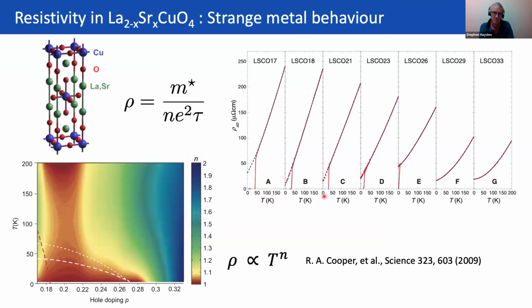So here's some paper from Nigel Hussey, who's going to be talking tomorrow. This is an old paper in Science which shows the linear resistivity in LSCO, and how it varies across the phase diagram, and you can see in this region here how linear it is. If you go to higher doping, it starts to look more curved, more T squared. And of course, for the underdoped region, you get the pseudogap. So the sample that we particularly studied was somewhere between 21% and 23%. So we'd expect it to have a nice linear resistivity.